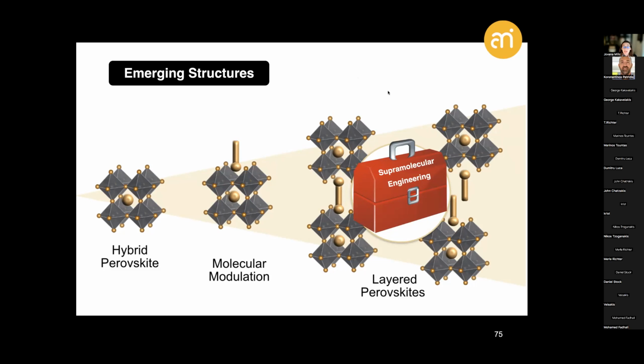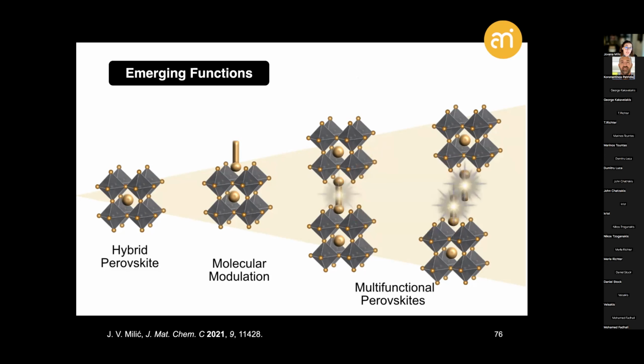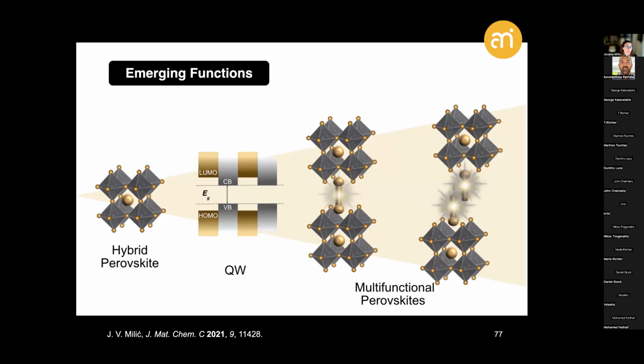of the organic component and introducing additional functionalities within the organic layer, that is especially relevant in these extended layered perovskite architectures that commonly have typical spacer components that are electronically insulating, behaving as quantum wells, where the charges are primarily confined to the inorganic framework that defines the resulting optoelectronic properties, that can be altered by tailoring carefully the organic component to access other quantum well structures where the organic component, that is